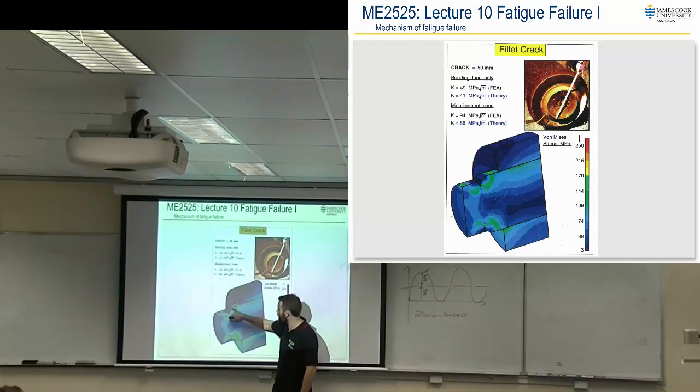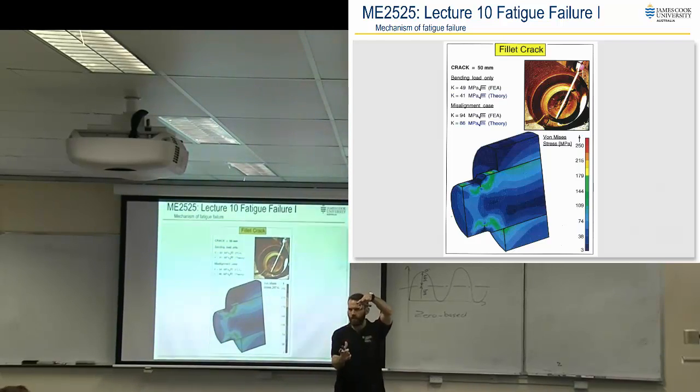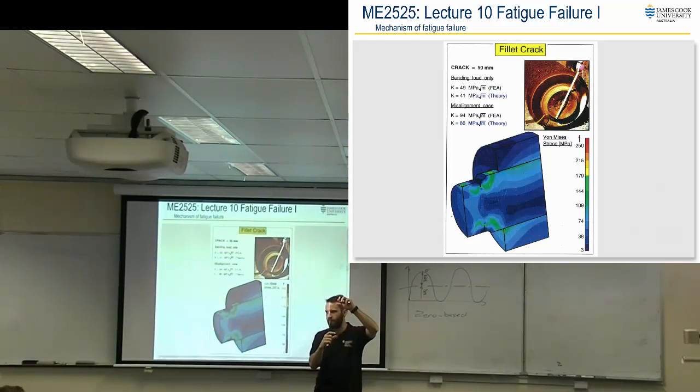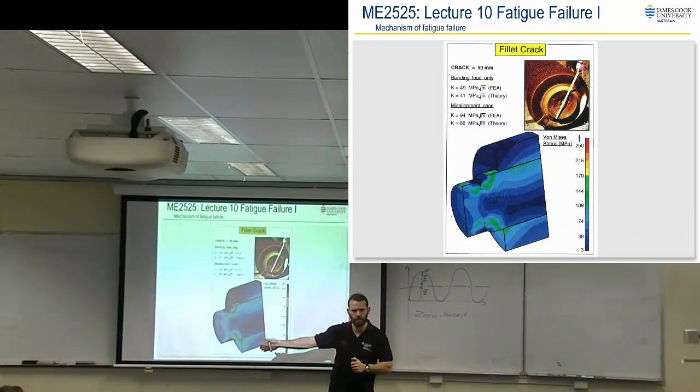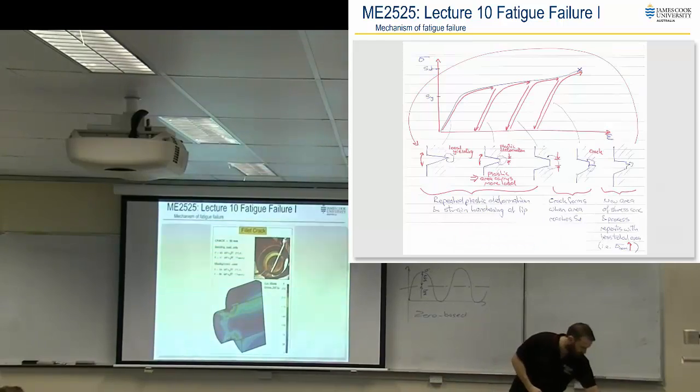The stress then reroutes down past that concentration, and it gets worse and worse and worse until the tipping point, which is once the actual area here, so you've got a certain amount of loading, right? And as that crack propagates, once that area, force on area, meets ultimate tensile strength, you'll just have static failure at that point. So the crack propagation will either happen for a very short amount of time or a very long amount of time, but the instantaneous catastrophic failure happens via static failure. But you get there because that crack propagating decreases your area until you meet the right criteria. So that's effectively what they're modeling there.